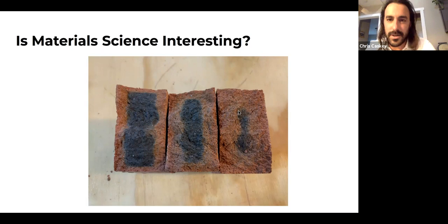So we don't need to eliminate this. This is called a black heart, because the brick industry is somewhat metal, but we don't need to eliminate black hearts because it's okay. It doesn't hurt anything unless we get to a temperature where the clay body has sealed up and lost its porosity, but we're still generating volatile materials from the inside of the brick, and then it'll puff up like a loaf of bread.